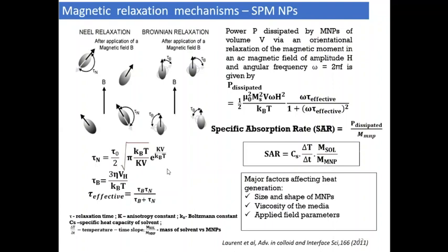Susceptibility is generally termed as the magnetization versus the applied field. So if you apply a small field and you are getting higher magnetization, the susceptibility will be higher. And if you have to apply a high field to get the magnetization, then the susceptibility will be low. So we want higher susceptibility materials to increase this factor. This factor is a complex factor, and it depends on the complex part of the susceptibility of the material. So the specific absorption rate, this is the power dissipated, and as I reiterate, it depends on the saturation magnetization, the frequency of the applied field, the strength of the applied field, and the susceptibility of the materials, which finally decides the effective relaxation times.